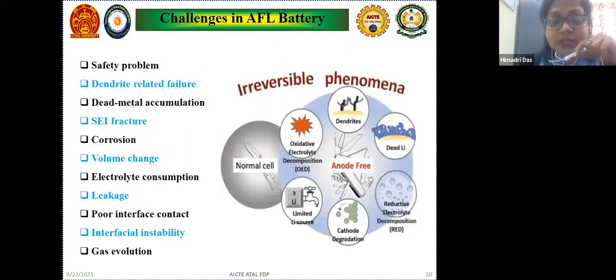If we study this anode free battery, we see there are irreversible phenomena, the same as dendrite growth and dead lithium, reduction and overconsumption of electrolyte, limited lithium source, cathode degradation, or oxidation of the electrolyte. As I explained, all these effects occur in lithium ion batteries as well as lithium metal batteries, and I think they are similar for the anode free battery. But when we are not using an anode, where do these effects come from?